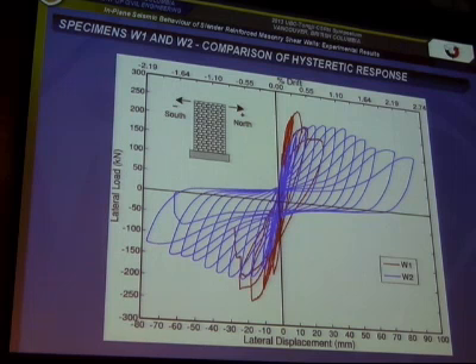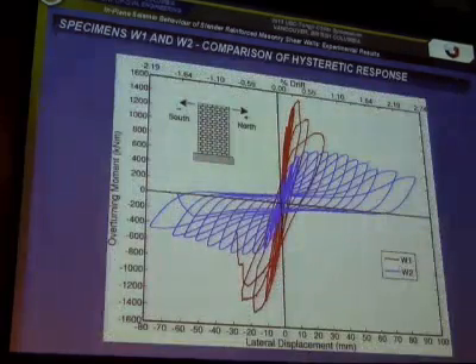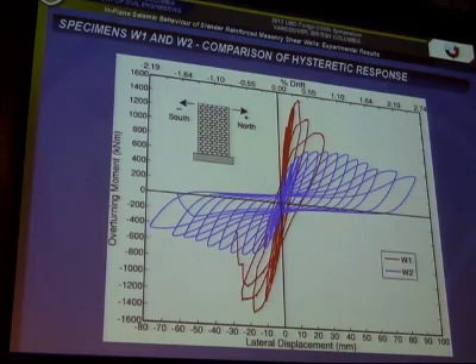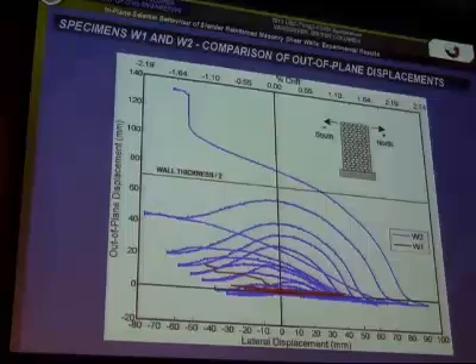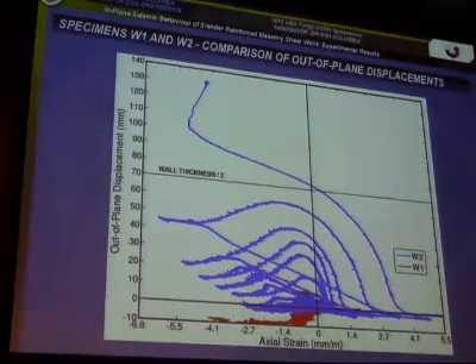Looking at the comparison of the responses of the first test, W1 in red here, and W2 in blue, you can see that there's quite a bit of difference in ductility, and a little bit in the lateral load capacity. The overturning moment is quite a bit higher in the first test, but still the ductility is much more in the second test. Looking at the out-of-plane displacements versus lateral displacement and versus axial strain, you can see that in W1, the first test, the amount of out-of-plane displacement is quite insignificant compared to the second test.